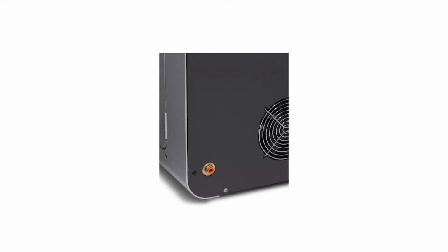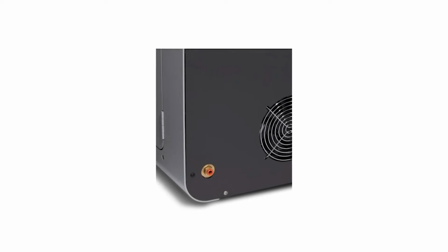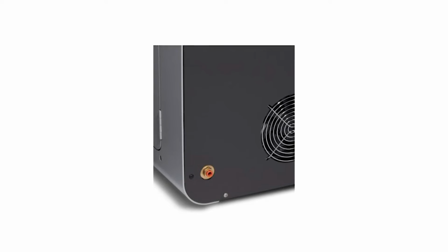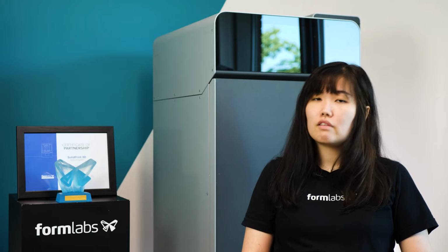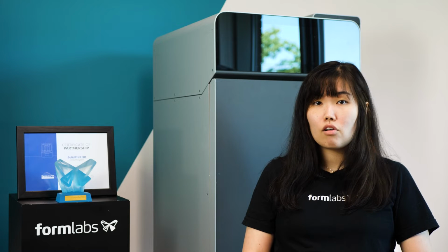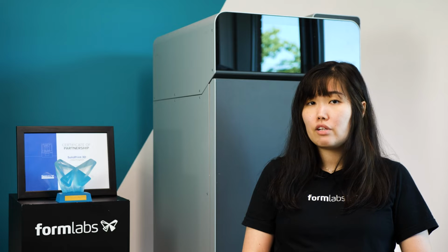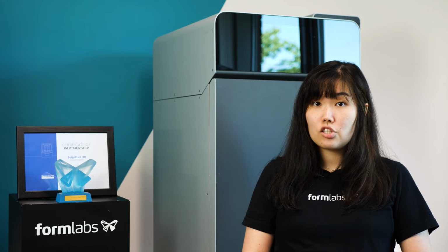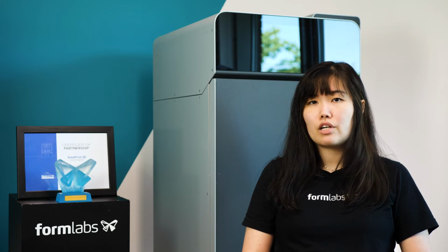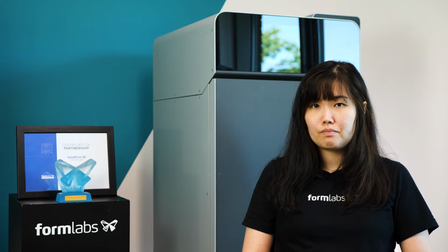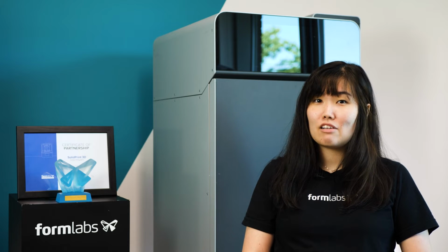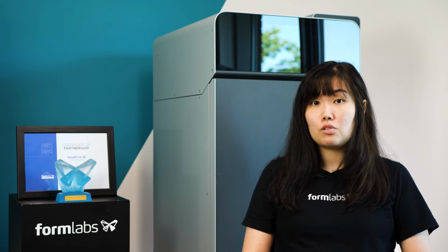By using nitrogen generators and nitrogen supply, you can essentially use the printers with a lower refresh rate. To give you an example, Nylon 11 running on air has a refresh rate of 50%, whereas with a nitrogen supply, the Nylon 11 refresh rate will go down to 30%. A lower refresh rate essentially allows you to save money and also reduce waste.